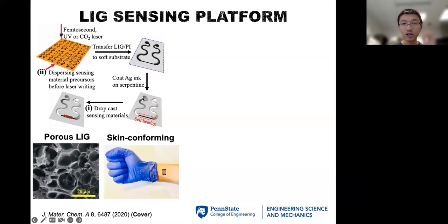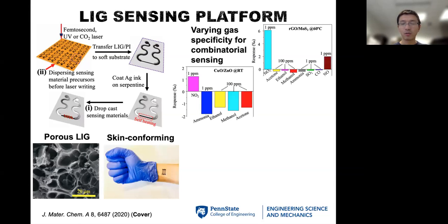And you probably notice a color change is to modify the surface of this interconnect region of the serpentine shape, and that further reduces the resistance from a few thousand ohms down to a few ohms. So when you pass the current to measure resistance, you will create a huge localized temperature increase because of the Joule heating, and that eliminates the separate heater from the beginning. So everything will be as simple as a single wire, but we will be able to integrate the highly sensitive detection with the heater from the self-heating. So that gives us a really nice platform to detect biomarkers in terms of different gases.